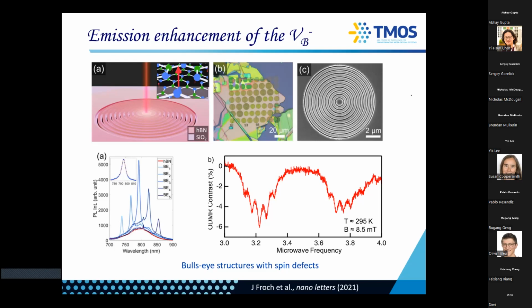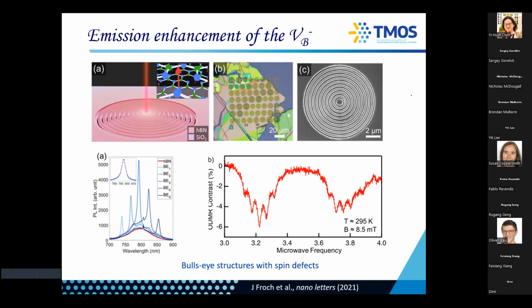Obviously, if you design it properly, the ODMR is beautiful because your signal to noise ratio goes up. And so you can really resolve the hyperfine splitting. So this is just the hyperfine of all the surrounding nitrogens, which is nice, but again, no single emitters. Even if we implant directly in the middle here, a very low dose of boron vacancy ions, no singles. Okay, so what do you do next?